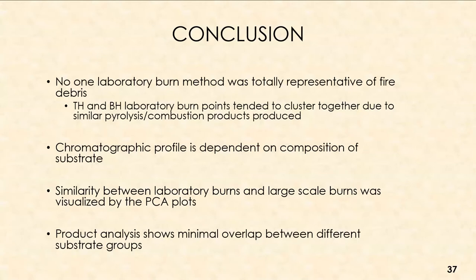In conclusion, there was no single laboratory burn method that was totally representative of fire debris. Top heat and bottom heat clustered together due to similar pyrolysis/combustion products and similar ions. The chromatographic profile is always dependent on the composition of the substrate — what additives, adhesives, fillers, glues, or fire retardants were applied, the burning environment, and ventilation all play a role. A similarity was observed between laboratory burns and large-scale burns, as visualized by PCA plots, with burns projecting within comparable regions showing similarities and differences.